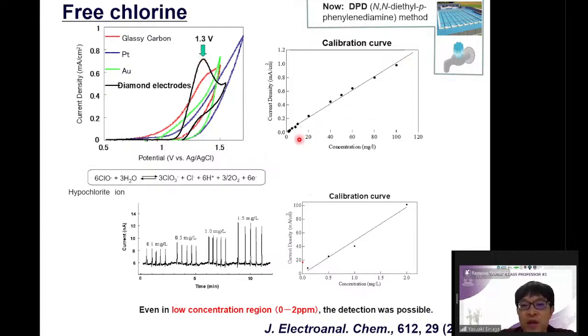As you can see, not only in this region, but also in the very low concentration region. For example, tap water analysis is possible, since it is possible to detect in this very low concentration. Okay, so this is the advantage of the diamond electrode. We reported this result in 2008, a long time ago. Then this result was sleeping for a long time.